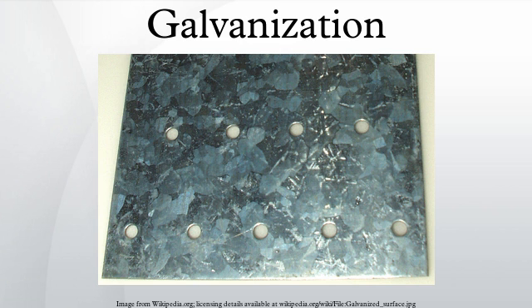Galvanized piping. In the early 20th century, galvanized piping replaced cast iron and lead in cold water plumbing. Typically, galvanized piping rusts from the inside out, building up plaques on the inside of the piping, causing both water pressure problems and eventual pipe failure. These plaques can flake off, leading to visible impurities in water and a slight metallic taste.